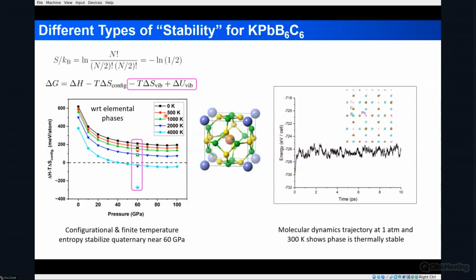But if you then consider other factors, for example, the finite temperature effects on the Gibbs free energy, and also potentially configurational entropy. What I mean by configurational entropy is if we assume that there is no site preference for the potassium and for the lead in a really large system where you could have disorder on the metal sites, then this would introduce configurational entropy that could be used to stabilize the system. And taking these types of situations into account suggests that this type of solid could be made under pressure and potentially quenched to atmospheric.